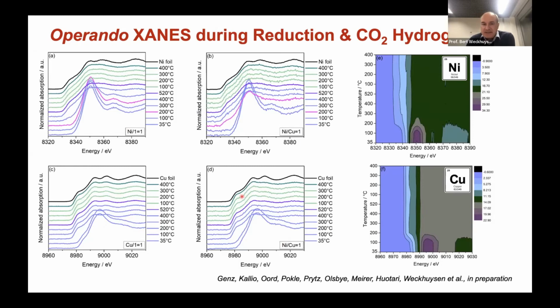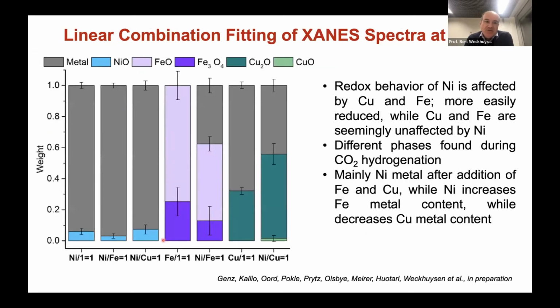If you now analyze that and you determine, via linear combination, the different species which may be present, and I have to make this warning because it is, of course, an assumption what you put into this fitting, then you see that for the nickel, you have mainly the nickel.